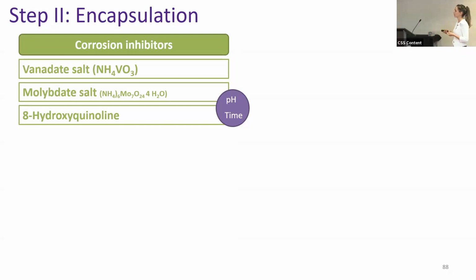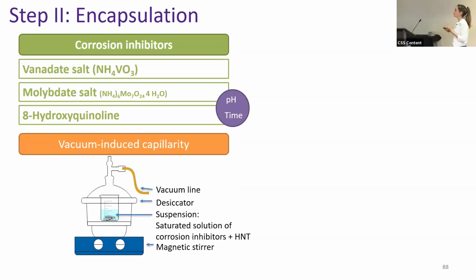While in the case of the organic corrosion inhibitor, the 8-hydroxyquinoline, this is a neutral molecule, so there won't be any type of electrostatic interaction with the nanotube, so the release will be time-dependent. We loaded the nanotubes via vacuum-induced capillarity, and this is the experimental setup that we use for the loading.